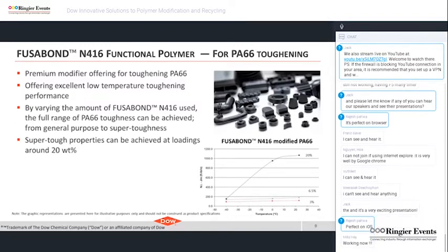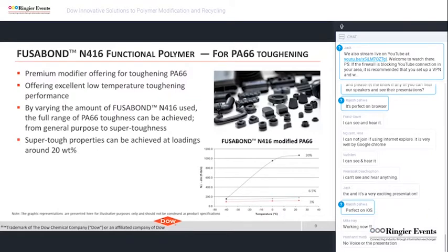Fusabond N416 is premium modifier for toughening PA66. Fusabond N416 offers excellent low temperature toughening performance. By varying the level of Fusabond N416, the full range of toughness, that is, from general purpose to super toughness, can be achieved in PA66. The chart shows super toughness performance at low temperature as well as room temperature can be achieved at around 20 wt% level of Fusabond N416. Since maleic anhydride level is high for Fusabond N416, it is not suitable for PA6.